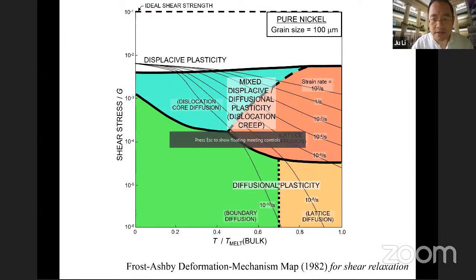So this is a very famous map called the Frost-Ashby deformation mechanism map. The horizontal axis is the temperature normalized by the melting point, and the vertical axis is the deviatoric shear stress, so the non-hydrostatic stress normalized by the shear modulus. This 10% is where the ideal strength roughly is. In traditional materials at low temperature, this is the yield. At high temperature, you have Coble creep or Nabarro-Herring creep. And in the middle, at intermediate temperature and stress, you have hybrid diffusive-displacive plasticity like power law dislocation creep.